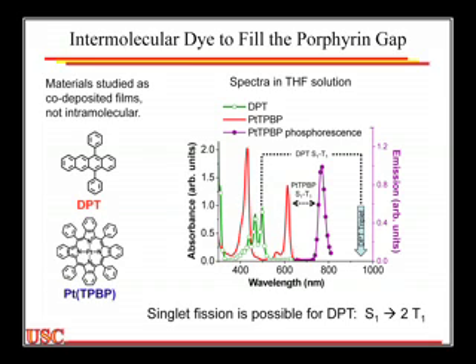So if I could do this in my device, that is to say, if I could collect all of my blue and green excitons, do singlet fission and double them and dump them into this red channel, then what ends up happening is I get no thermalization losses from here at all. I dump those into this channel. This red section still gives me a thermalization loss. But if you look at the numbers, Nozik and Michl have actually estimated that you can make a 45% efficient single junction cell using this approach. But the key is you can't give up absorbing these photons.